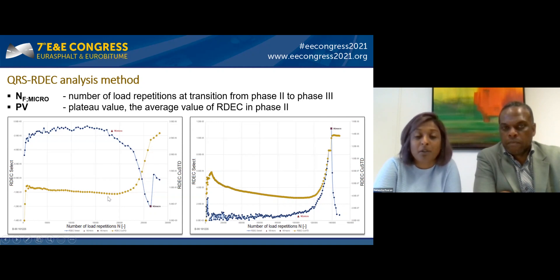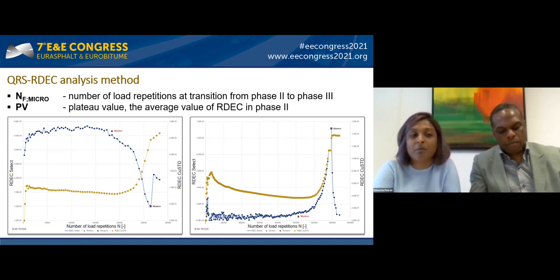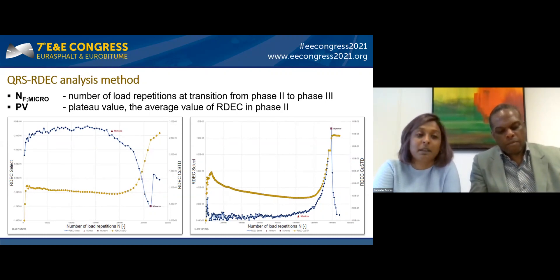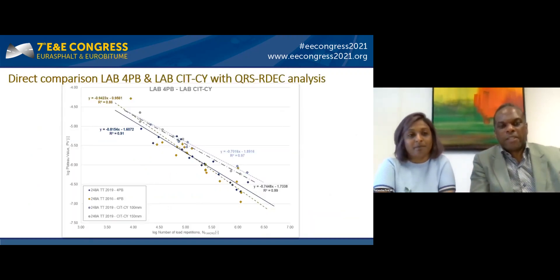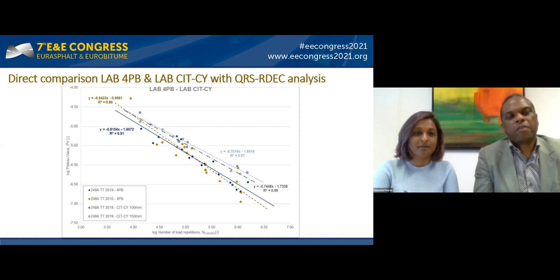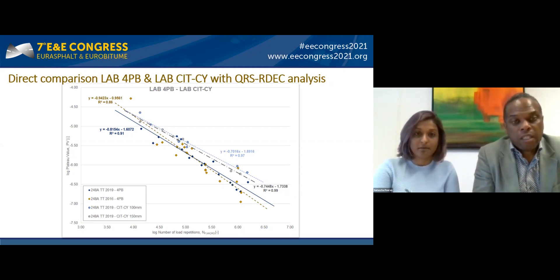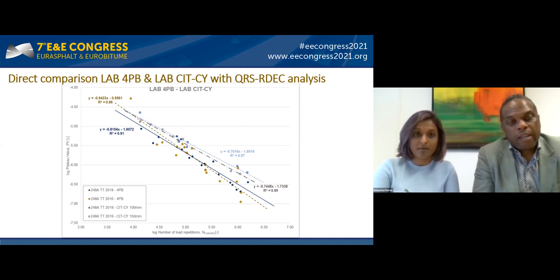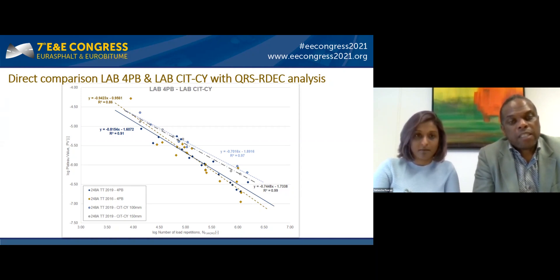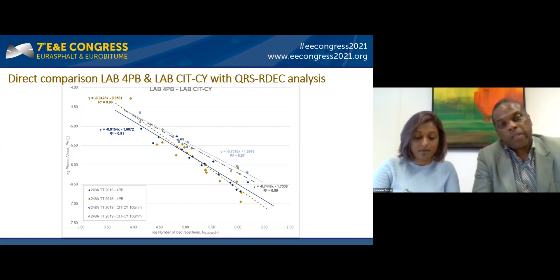Based on these starting points, we automated this RDEC analysis method and named it QRS-RDEC. We calculate the plateau value as described, and Nf micro is determined by calculating the cumulative standard deviation of RDEC and taking the number of load repetitions at the minimum of this cumulative standard deviation. Using this method we analyzed fatigue data from type tests and from material from the road.